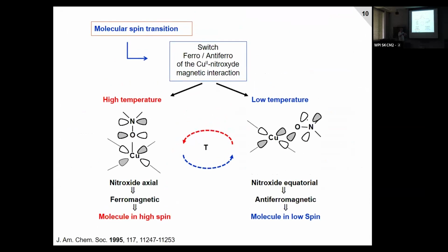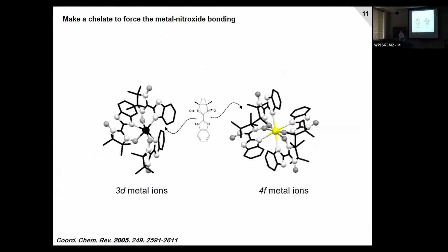With nitroxide and metal ions, the conformation of the radicals regarding the metal ions is very important for the kind of interaction, because the conformation will depend on whether the orbitals of the radical and the metal combine. So with this strategy, we have the possibility to use almost all 3d metal ions. For the 3d metal ions, we always put 3 radicals, and for the non-3d ions, we can put 4 radicals.